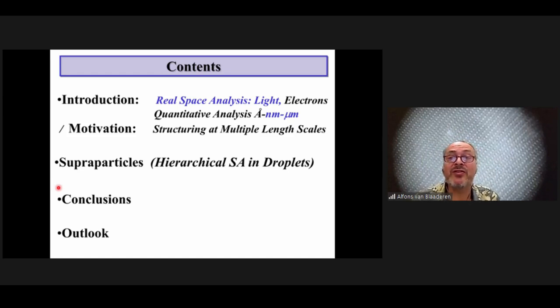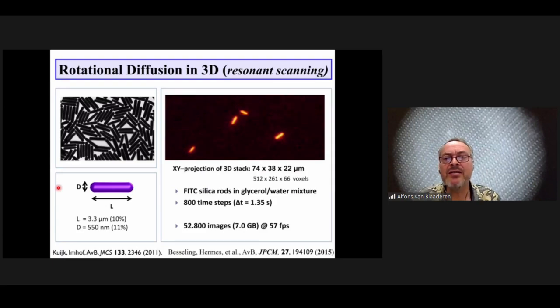But we've also ventured into electron microscopy tomography to elucidate, also on the nanoparticle level, quantitatively in 3D, the structure of these self-assemblies. What is new in light microscopy, and we are now pushing that all the way to nanoscopy, so even having three-dimensional resolutions below 100 nanometers, is that we can not only determine in 3D the positions of spherical particles, but also of rod-like particles, and then also obtain the positions of the rods, but also their orientation in 3D. We can scan very fast, so extensive three-dimensional data sets can be scanned within on the order of a second.